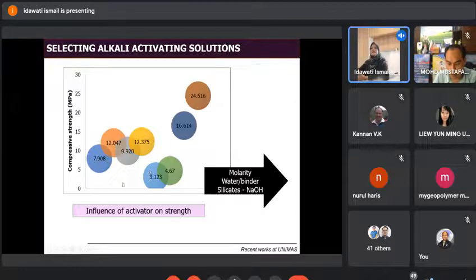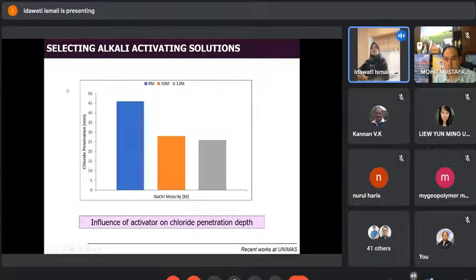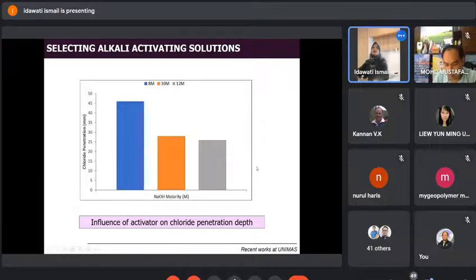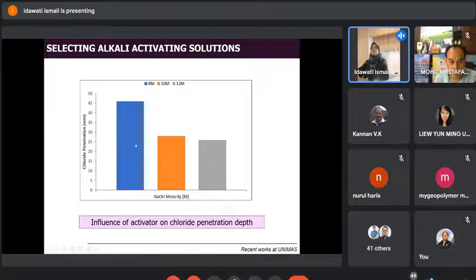Currently, my PhD and master's students are looking into all types of mixes as a function of molarity, water binder, and activator types. This is how activator influences chloride penetration. You see that the 12 mole of sodium hydroxide gives lower chloride penetration. This is also the case for locally available fly ash in Sarawak right now. So 25 mm penetration, also tested under the NORD test.